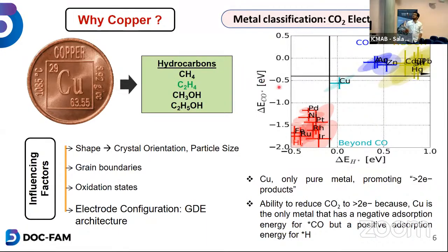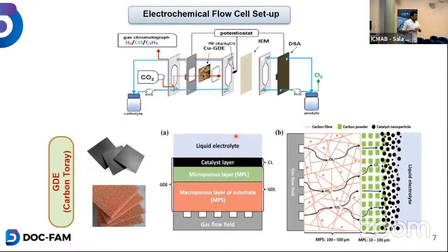When we take it to the metal classification, it is the only promising metal that can promote electron transfer reactions of greater than 2 electrons. And when we see the adsorption isotherms, it is the only metal found to have a positive adsorption energy for hydrogen and a negative adsorption energy for carbon monoxide. As CO is a key intermediate in forming the next products in the CO2 reduction direction, I think copper is found to be the most promising material, or we can call it a benchmark material. So copper is a very good material to focus on. So what do we do with the copper?